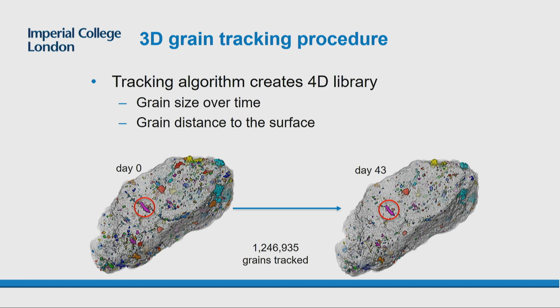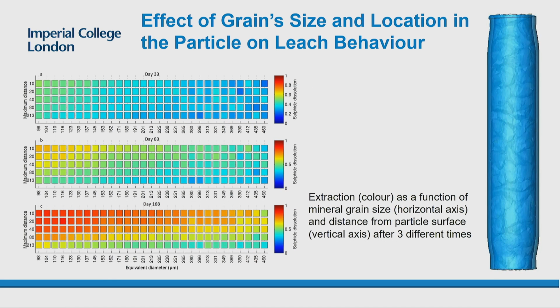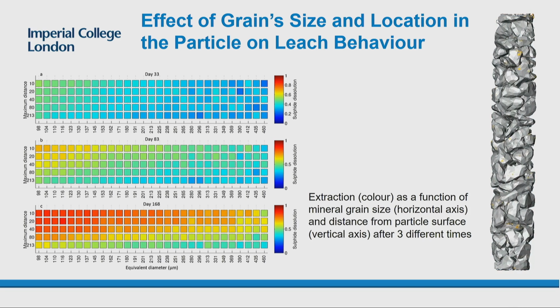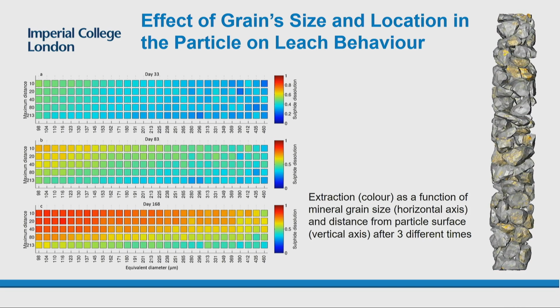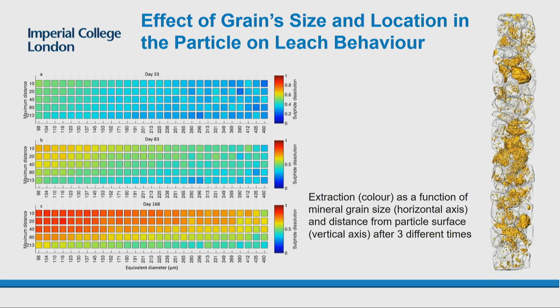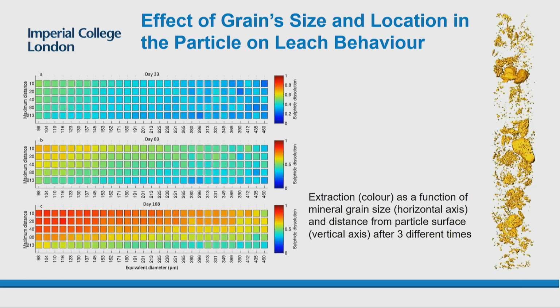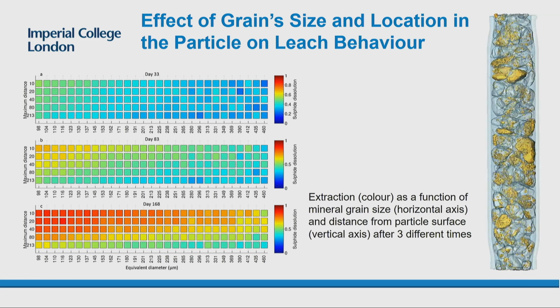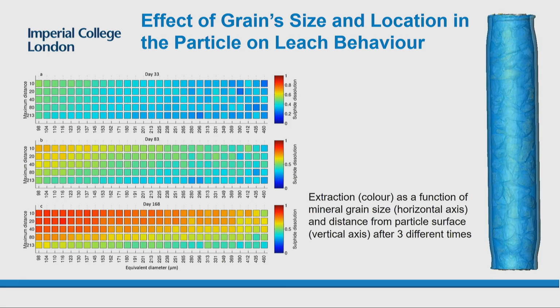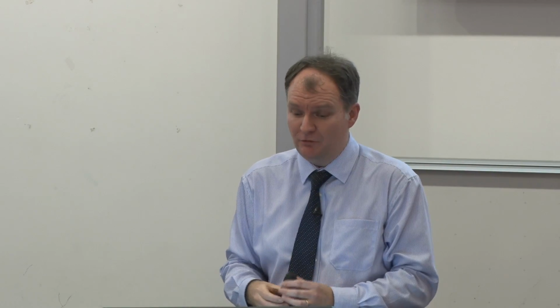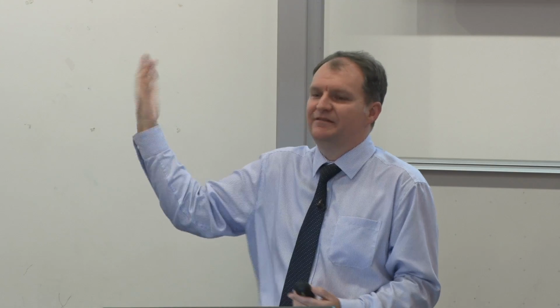And this allows us to actually look in detail at what affects the performance. These graphs are showing on the bottom axis the size of the individual grains and on the vertical axis how far from the edge of the rock they are. And as you would expect, small grains leach quicker than big grains, and grains near the surface leach quicker than grains very deep inside the rock, which of course is obvious, but at least we can actually quantify the relative importance of these effects. And they are quite significant.